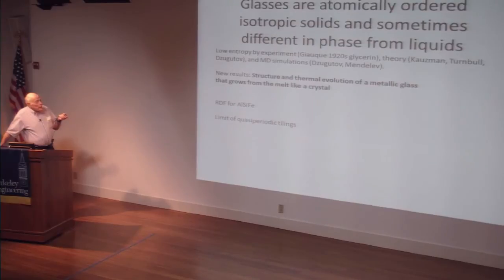But Mendelev, who's at Minnesota, has done an MD simulation on aluminum. And he finds that there is a metastable phase which is isotropic, and it coexists with the liquid. And there's a melting point of it. When you heat it, the interface between the liquid and this glassy phase moves up, and if you cool it, it moves down. It isn't that the glass melts by uniformly melting or forms by crystallizing.